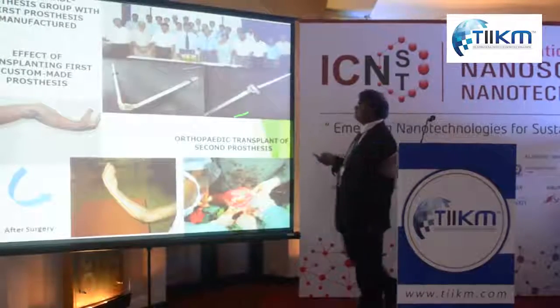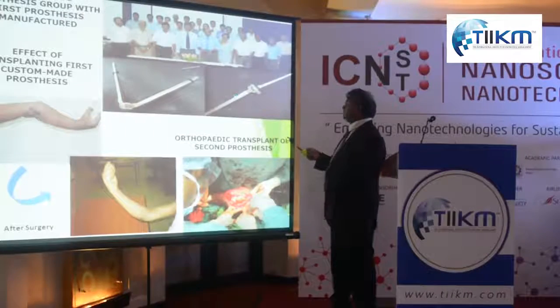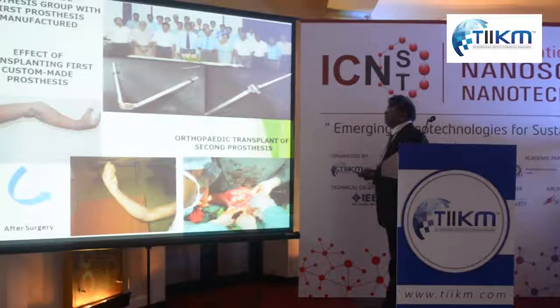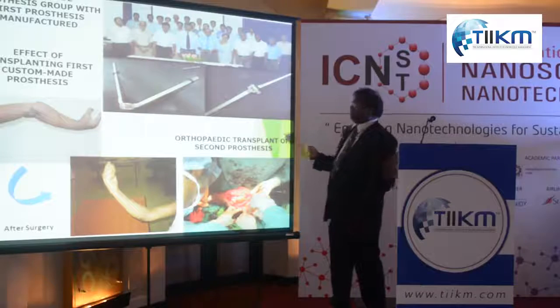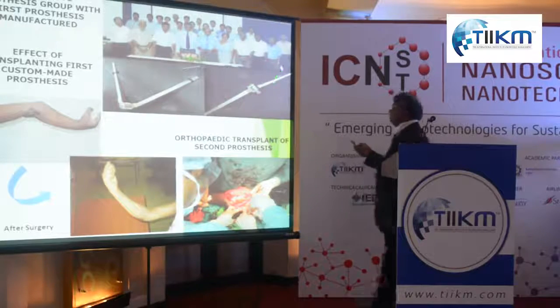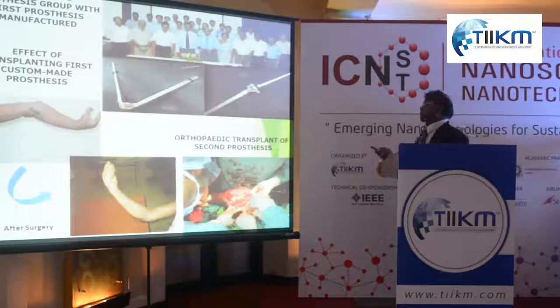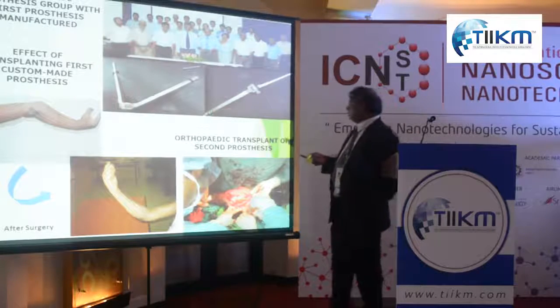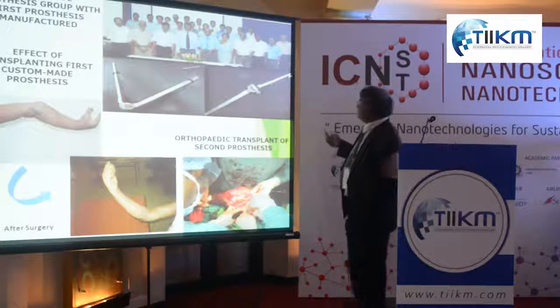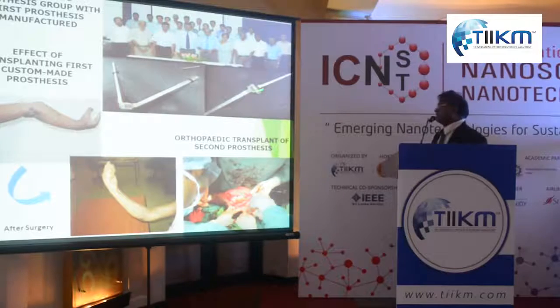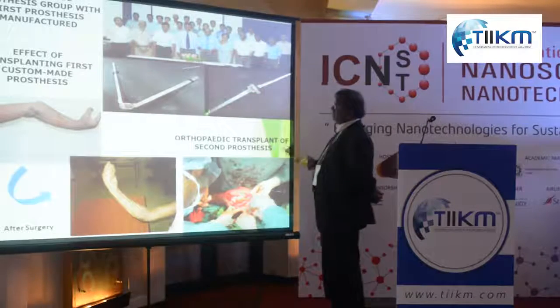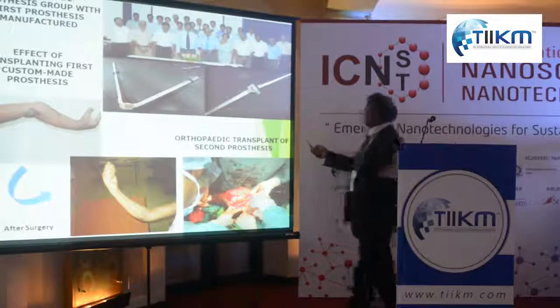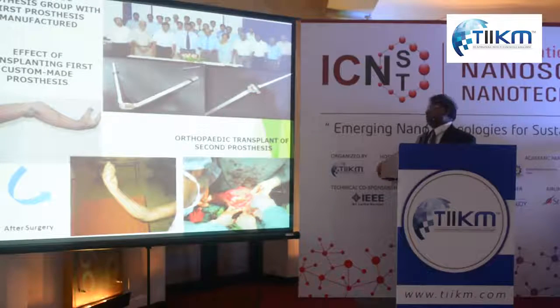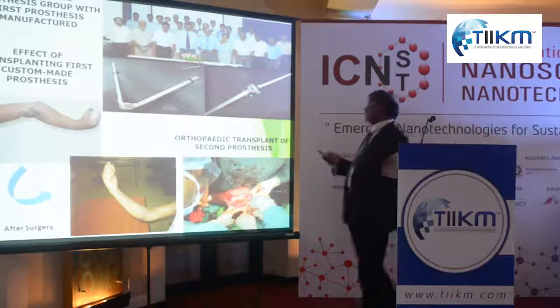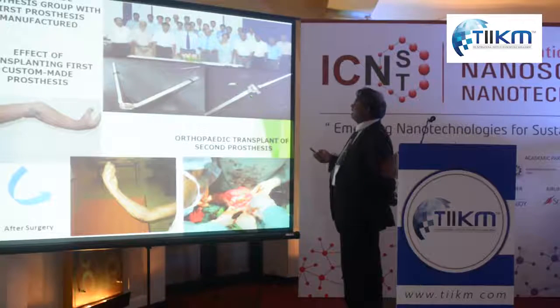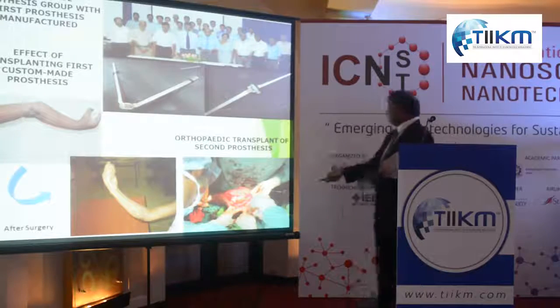So what we did was we wanted to deposit hydroxyapatite nanoparticles on them. But just on the stainless steel, very difficult. Stainless steel is very inert, very difficult to attach anything chemically. So we did a trick. Titanium dioxide is an amazing material. It sticks on many surfaces, including stainless steel. Using our instrument, we use a very thin layer of titanium dioxide on stainless steel, on which we developed hydroxyapatite coating. And collagen is the biopolymer you have.